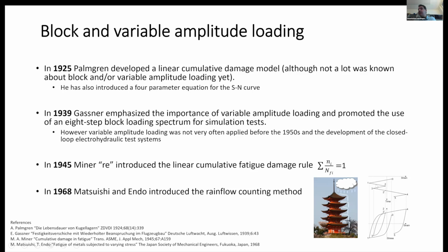And in 1968, some Japanese scientists, the first of them Matsuishi and Endo, introduced the rainflow counting. So the idea is how to measure how many cycles we have in every variable amplitude loading that we meet in reality. They were inspired by the way that raindrops fall in a pagoda, and so it comes down. This is exactly what they do in cycles. When it comes down like that, they count a cycle in between. So that's why they call this the rainflow counting method, because it measures the cycles in a way that the raindrops go down the pagoda roofs.